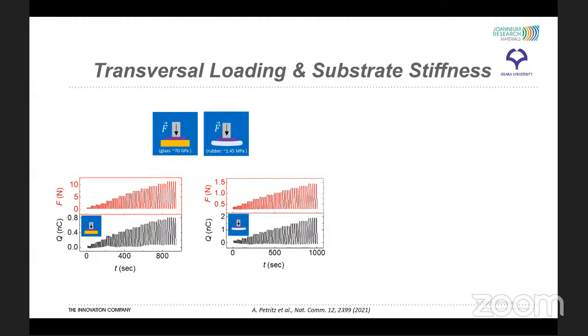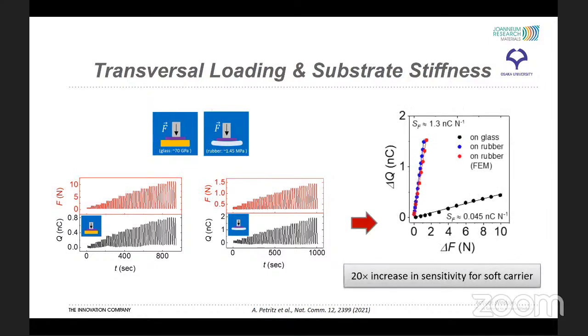Then we investigated the sensor response under transversal loading by a stamp, where we see a clear difference whether the sensor is attached to a rigid support like glass, plotted on the left, or to an elastic support like rubber, plotted on the right. In both cases, the charge response curve correlates in shape and dynamics with the exciting force curve. But we observe a strong, more than 20 times increase in sensitivity for the same ultra-flexible sensor when attached to rubber instead of glass.